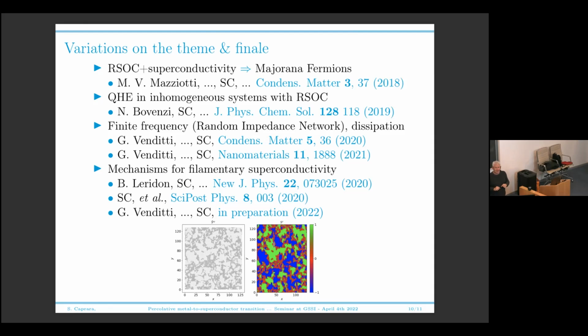very simple-minded model. Imagine that you have a Heisenberg spin. This spin can point along Z positive, along Z negative, and we map these two solutions, positive Z magnetization, negative Z magnetization, and two different ground states of, say, a charge density wave system. Why? Because in cuprates, superconductors, and other systems, charge density wave is a phase that seems to compete with superconductivity. Superconductivity is instead a situation where the spin is in the plane XY.